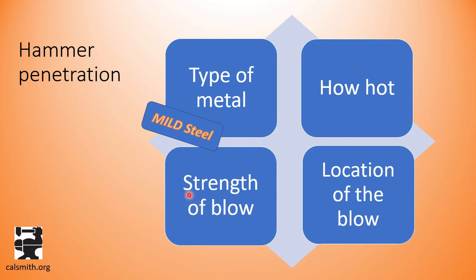The next factor is the strength of the blow. A lot of people think that you really got to hit your metal hard in order to weld it. In fact, that is the opposite of the truth, in that a hard, heavy blow is only going to deform your material or forge it and not weld. So you want to use light to moderate blows.